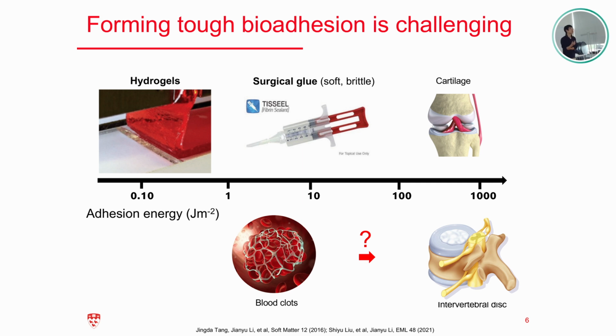And a little information about this property we use, adhesion energy. That is the energy needed in order to peel a unit area of a material from a substrate. So that is essentially based on the energy principle, how much energy you need to peel it off. And as you can recognize here, for the order of magnitude, the adhesion energy of hydrogel essentially is the surface energy of the water, right? After the peeling, you are creating a new surface of the water. And that makes sense why the hydrogel suffers from weak adhesion.